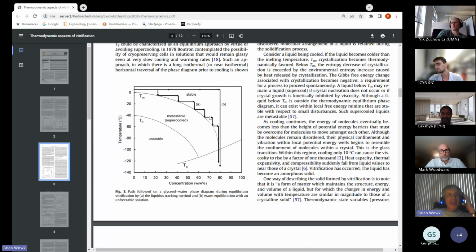So for example, if you put in a concentration of CPA at -130 that has a melting point of -40, and you expose cells to that at -30, what's going to happen is water is going to osmotically migrate out of the cells until the inside of the cell takes on the same melting point as the solution that surrounds the cell, because melting point is actually a measure of water activity.